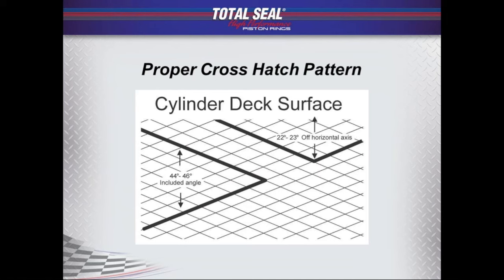The reason we do this is because crosshatch angle helps to determine ring rotation speeds. If we get a real vertical angle, a real steep angle, it's going to try to make the ring rotate fast. A very quickly rotating ring can cause the end gaps to line up. That's a fairly common issue if you've got an engine that's always trying to line the end gaps up. More than likely, it's a crosshatch angle problem. Too up and down, too vertical.